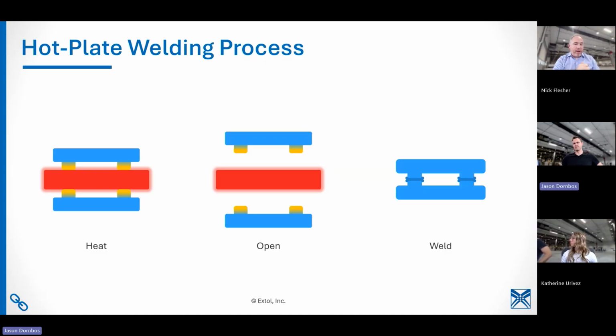Well, let's talk hot plate while we have it up, Jason. What do we typically say? Around 80 to 90%, if I'm not mistaken, if it's a 1-to-1 wall stock to weld. But I think if you do a 2-to-1 ratio of your weld rib to your wall stock, you can reach parent material, pretty straightforwardly.